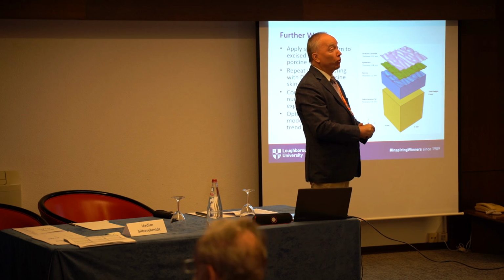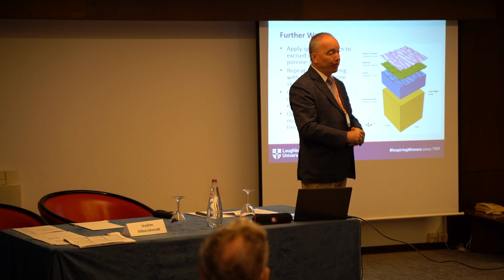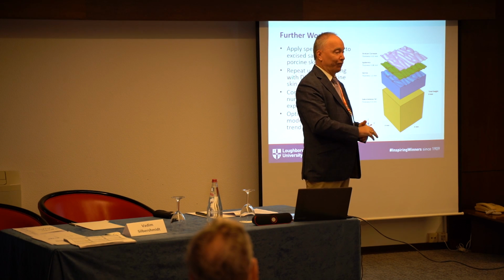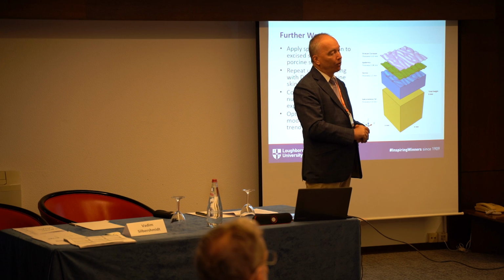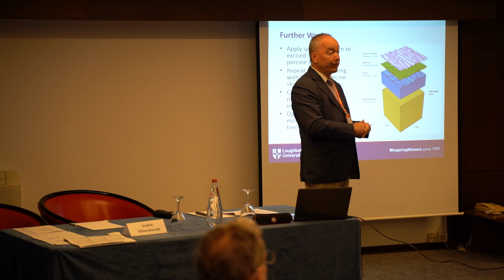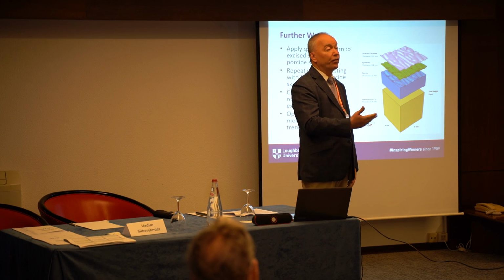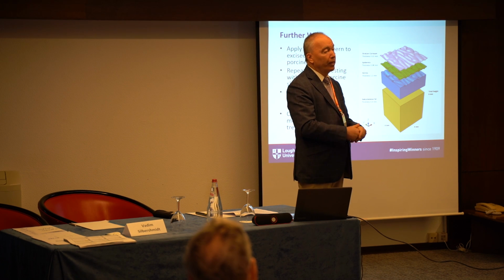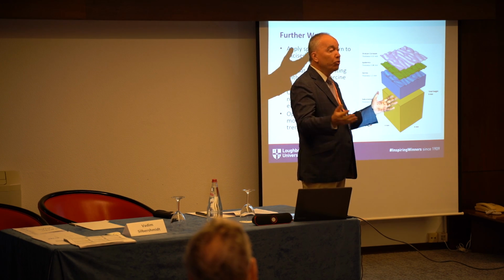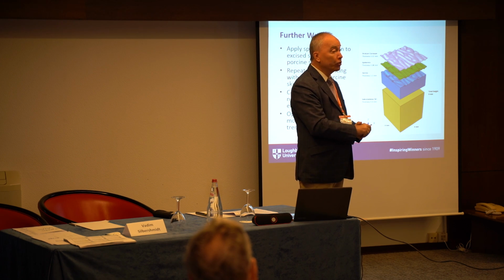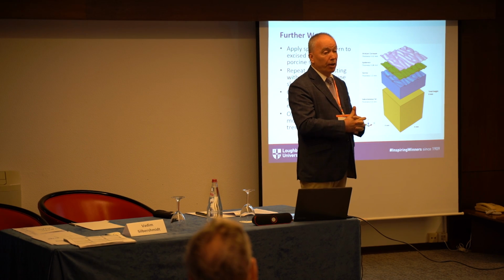So clearly, on a more serious note, when I'm speaking about the semi-inverse approach, we're running in parallel, so it's not really in real time because the simulations are long. We do the simulations and we are playing with some parameters which can prescribe or can affect, for instance, the friction or frictionless condition. For instance, you put here the oil, you don't put here the oil, and so on, and so eliminating the different factors. And then you are trying to match. So understanding that this is an ill-posed problem, but this is because we start with a rather close approximation to the model. This is the one.